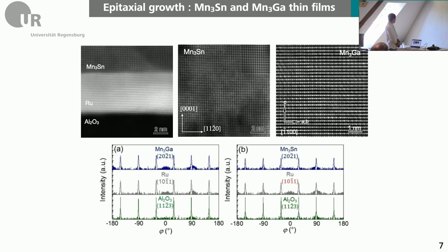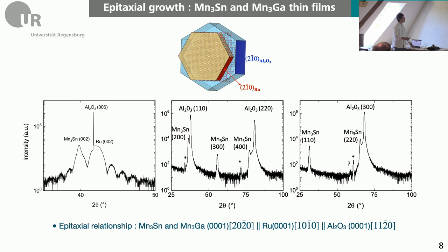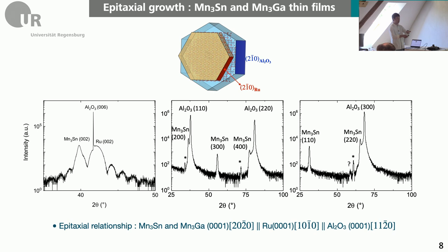This is the in-plane and this is the out-of-plane XRD. It tells you that our manganese-3-tin system was grown on top of the 0001 aluminum oxide substrate along the C direction. When you look at the in-plane directions, the orientation relationship between substrate and the main layer is 30-degree shifted, so that we can have, for example, the X axis of manganese-3-tin or gallium along the Y axis of aluminum oxide. This allows us to find the correct direction to measure the anisotropy of conductivity and transport properties, since symmetry is really important in this material.